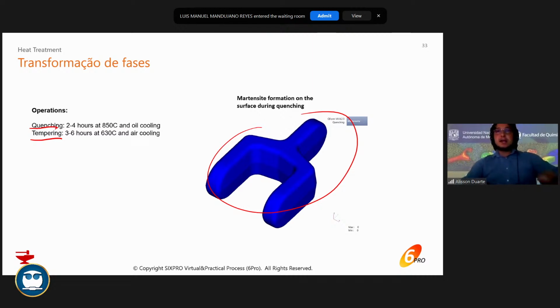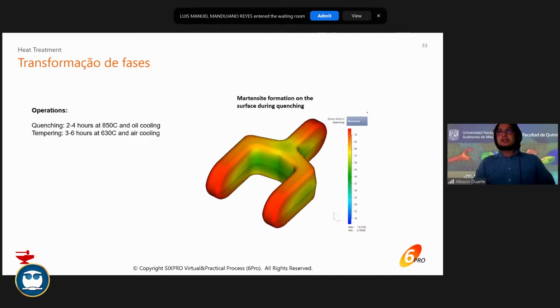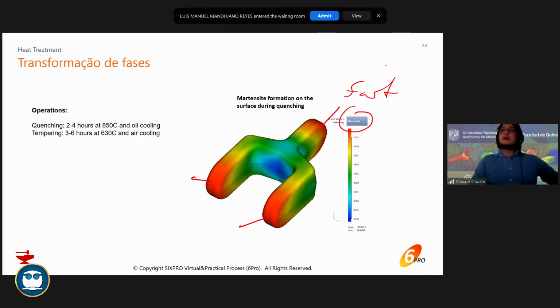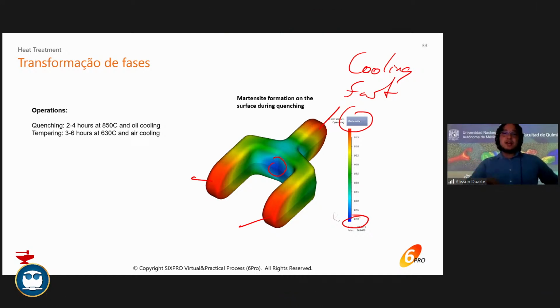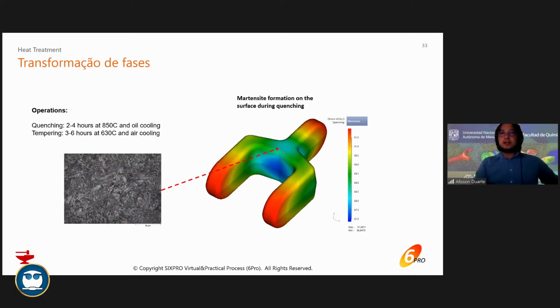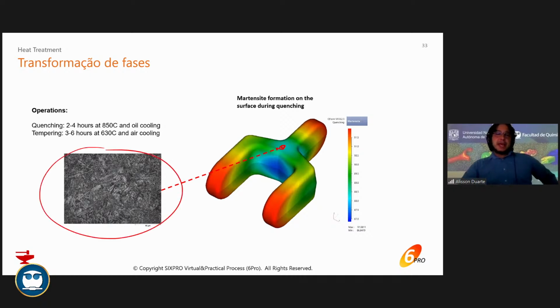industry. And here you can simulate the amount of martensite. Of course, here in those areas, you have much more martensite because the cooling is much faster. And here, the cooling is slower, so you have a lower amount of martensite. And then you have this distribution of final properties like hardness, mechanical resistance. So you have all of these. In this case, we have this checking point here, and you could see a lot of martensite there.